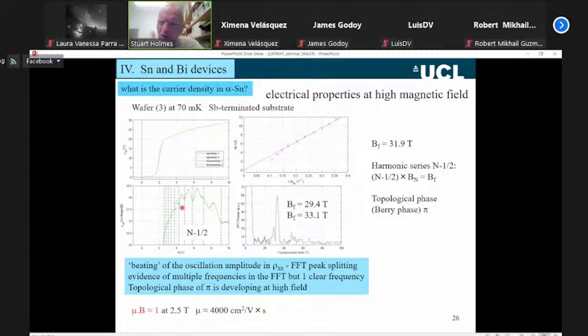If we expand those oscillations up, we see a whole series of minima here. What we also see in the material is something that looks like a spin splitting. So we get extra periods coming in here, but also that envelope seems to beat. There seems to be a kind of two frequencies that are matched. And if we do a Fourier transform of that, so what we show you here now is the Fourier transform of these oscillations. You can see the main peak has split into two, and it looks like a kind of Rashba spin splitting.